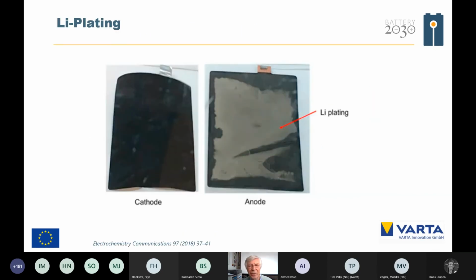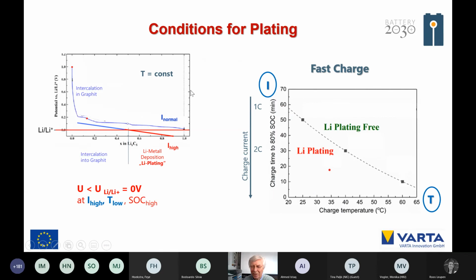So here you have some examples from real cells, and you can see by the color the anode: that is the normal one, the graphite, and that is a lithium plated one. So the conditions for plating, we mentioned high current and low temperature, because at low temperature the resistivity is increased and the curve is also decreased. And the temperature influence is really a problem for fast charge.